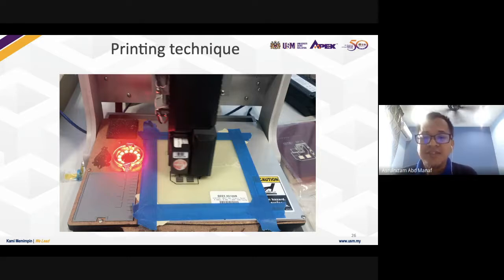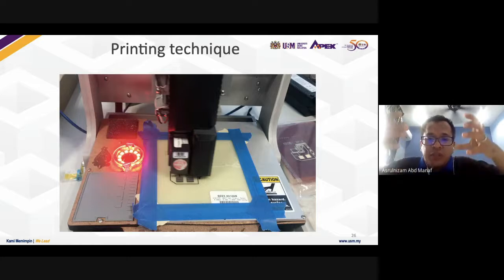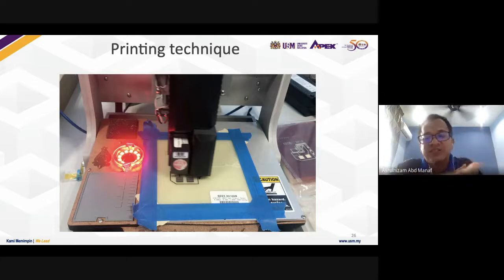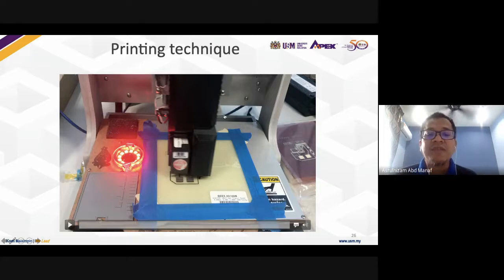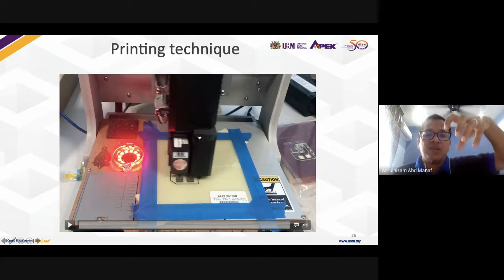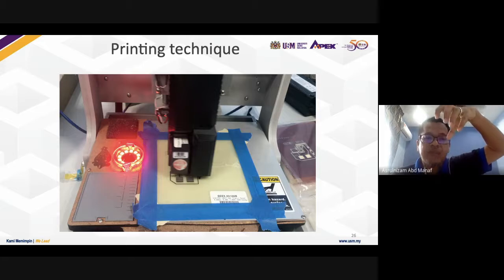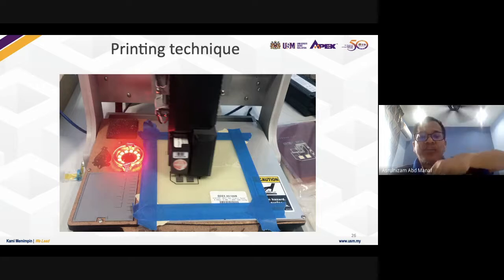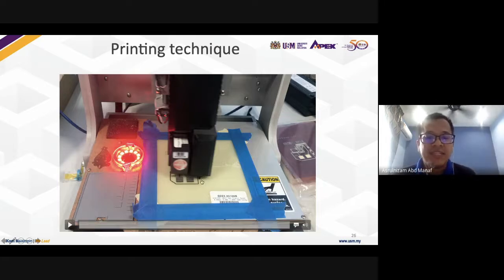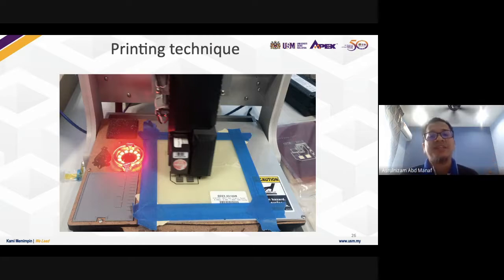Screen printing is easier because you just design a mesh and then you just screen print. But the problem with screen printing compared to inkjet is that you can waste ink. With inkjet you can minimize the volume, but the cartridge is too complex in terms of the sponge component, where you have to get the right volume of ink. If not, your ink will dry, right? And then second, the size of the nozzle must be considered with your particle size, that means your silver particle size.